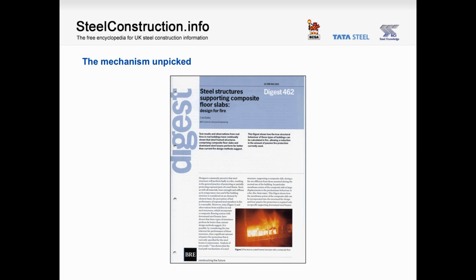The tests also enabled us to understand the mechanism by which the composite steel deck floors generate so much more capacity than is apparent from small standard fire tests. I won't go into the detail, but analysis of the test results has shown that the load path mechanisms of a steel structure supporting a composite steel floor during a fire are different from those assumed during the normal use of the building. In particular, membrane action of the slab at large displacements enables it to enhance its load carrying capacity, and this enhanced capacity is what provides the additional capability. For those who are interested in pursuing this further, details can be found in a number of sources, one of which is BRE Digest 462. The mechanism is sometimes called the Bailey method, after the person who first developed it.